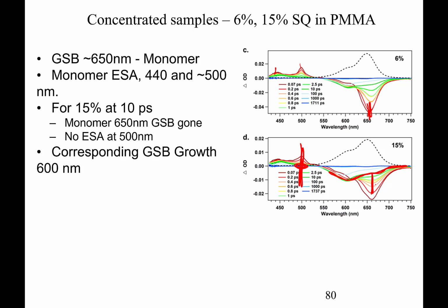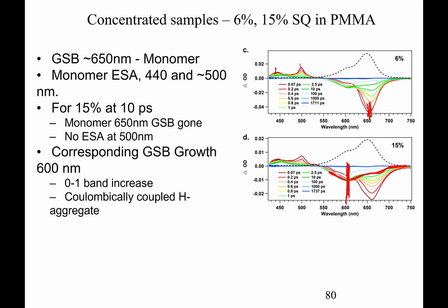What we find instead is we see a growth at 600 nanometers right in here, and that's a ground state bleach growth. It's the 0-1 band that increases. We claim that that is associated with a coulombically coupled H aggregate. So that's an H aggregate where these molecules stack together. The separation might be quite large at low concentrations, but as we start to reach around 15% doping, then these molecules start to see each other, they start to be a little closer together.